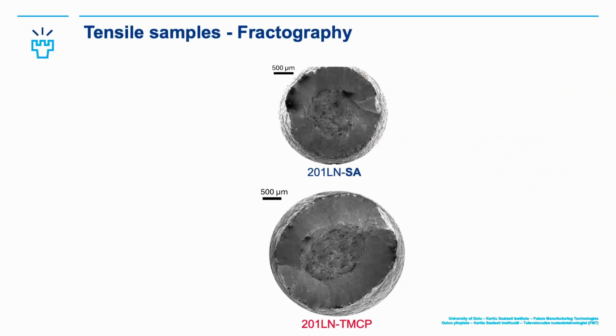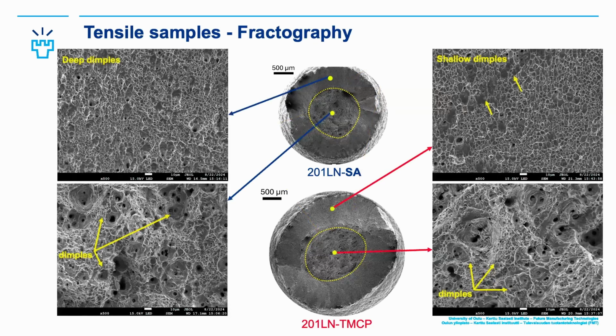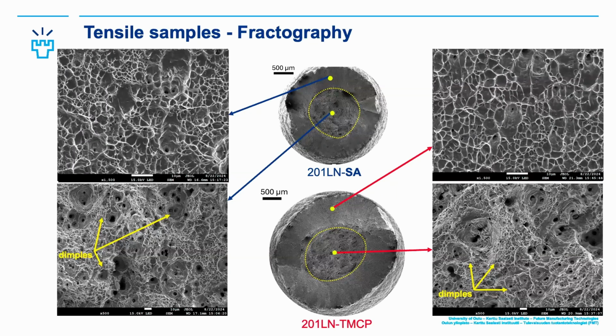And finally, for the tensile samples, the fractography. So in the beginning, we could see clearly, this is the sample from the TMCP plates, and this is the solution annealed, and this is a relative scale. So we could see here that the ductility, the reduction in area, is quite higher. Microvoids and shear zones are quite clear, and SEM images also show the dimples, but in the shear zone we have deep dimples for the solution annealed and shallow for the TMCP plates, which are quite common features for this kind of failure. And this is a zoomed in SEM.